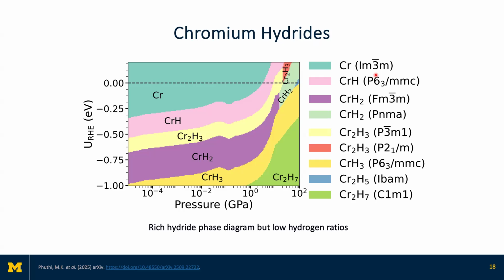You need that coupling to be very strong, on the order of more than one. You need a very high density of states near the Fermi level. This has to do with the electronic structure, so you have to be metallic. At the Fermi level, you need a relatively high electronic density of states. Those are the two major ones. They don't interplay perfectly, but in general, strong electron-phonon coupling, high density of states.